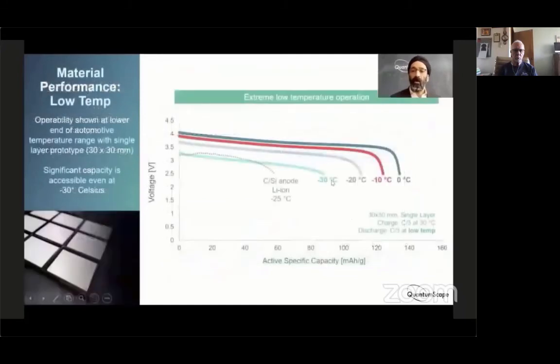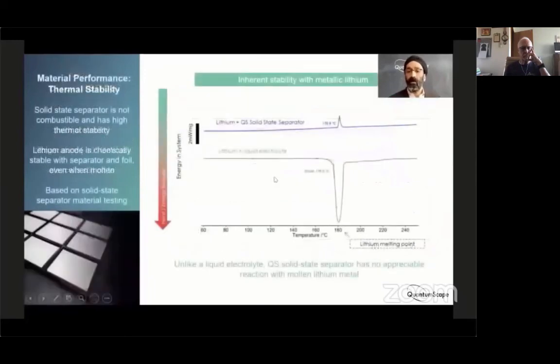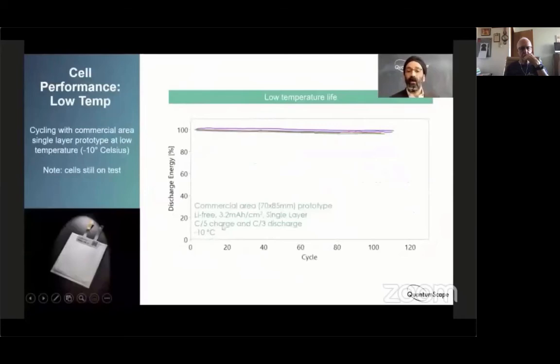So super exciting result. Another limitation that solid-state batteries sometimes have is they only operate at elevated temperatures. To demonstrate that we don't have that limitation, we have taken our material and tested it all the way down to -30 degrees, and you still get substantial capacity out of the cell, even at -30. By contrast, lithium-ion technologies would have less capacity than we have even at -25 degrees. And finally, on the temperature side, we do cycle these cells at -10 degrees. And again, these are commercial area cells with fully loaded cathodes and lithium-free. And you can see these cells cycle very well with minimal degradation. This is a new batch of cells we put out recently. So it's achieved about 100 cycles.